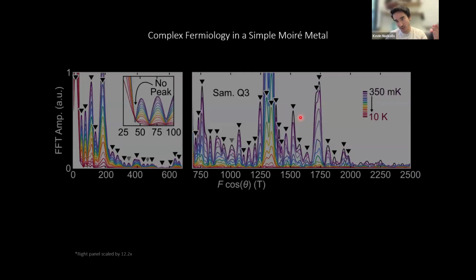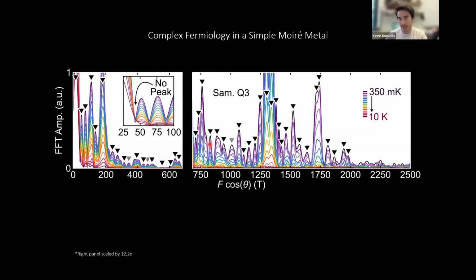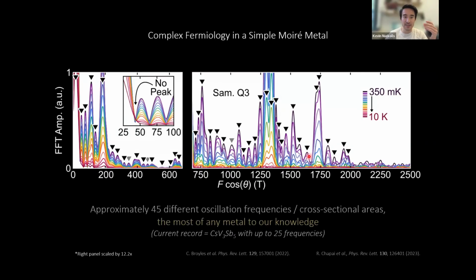And we find nearly identical Fourier transforms that are very complicated in this crystal. So like the other bulk Moiré metals, we have this dense cascade of low frequency pockets, but now this cascade persists all the way up to much higher frequencies, much bigger pockets. In total, in comparing these two measurements that I'm showing you in the main text, we find that approximately 45 different quantum oscillation frequencies or cross-sectional areas are shared between these measurements, which to our knowledge is the most that's ever been seen in a metal.